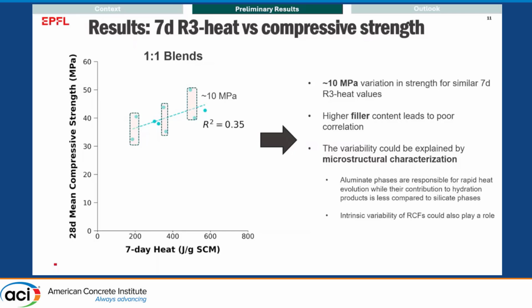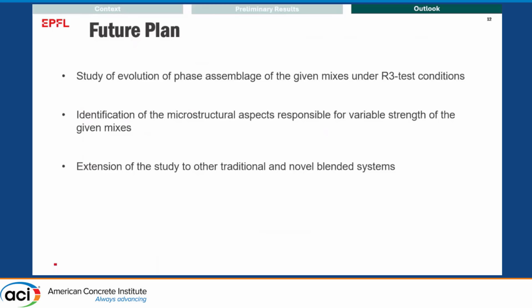Another thing to note is that recycled concrete fines have variable properties. When you do strength tests with the same sample twice, the results might not be as similar as we think with other SCMs. So there are some challenges to deal with, but this will be dealt with in my future work, where I'm going to study the evolution of phase assemblages using XRD, and also look at microstructural aspects, porosity aspects, and extend this study into other traditional SCMs, because so far I've talked about LC3 and RC3, but we can also see how combinations of other SCMs perform with respect to R3 heat.